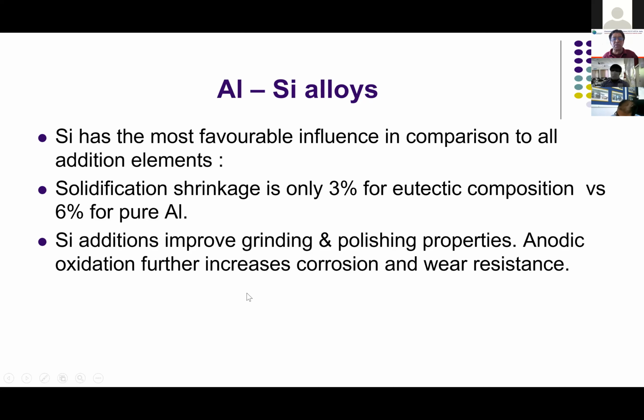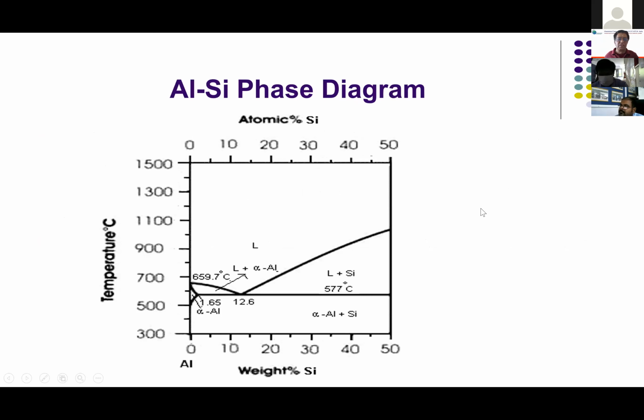Silicon addition improves the grinding and polishing properties. Nowadays the castings need to be finished after proper machining and all. So silicon to a great extent improves the hardness and improves the grinding and polishing property. Anodic oxidation further increases corrosion and wear resistance. Wherever you expect a corrosive atmosphere and where there is going to be a requirement for wear resistance, silicon is your main alloying element.